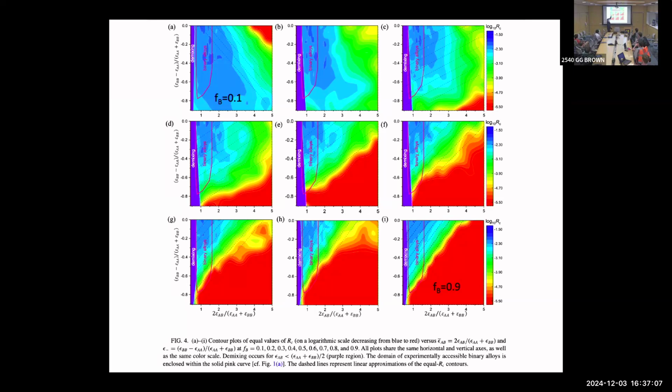And then when you're in a middle region, when you have enough A's, where should the red be? Well, I'm looking at the difference between the cohesive energies. You can't get a glass if the cohesive energies are the same. If they're both the same, why would it form a glass? Same thing here. You want epsilon AB to be relatively large so that you encourage mixing of the A's and the B's. So in general, I hand wave that the glass forming ability is going to be on the right.